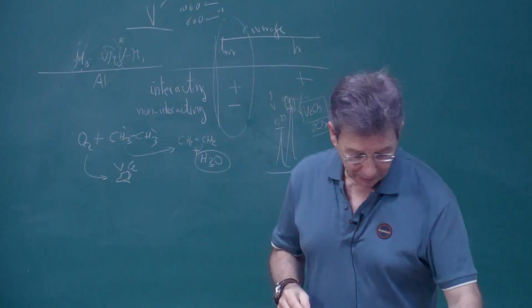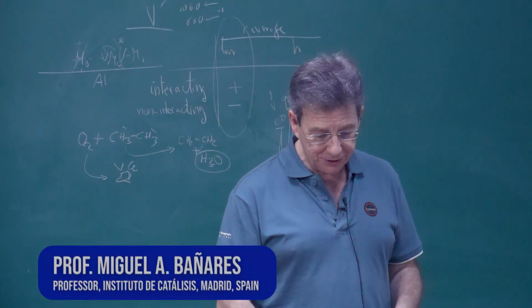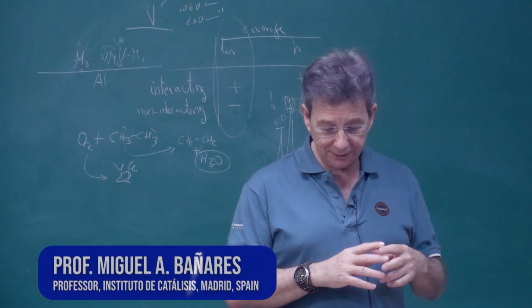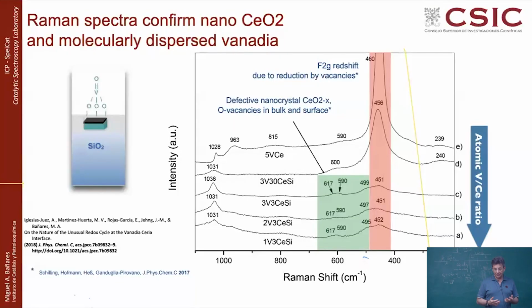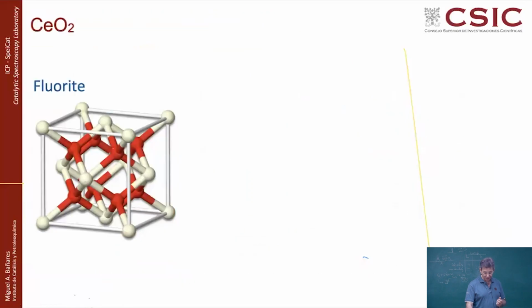That I missed, and I'm just showing it here, which is when we are using the nanoscale ceria on silica, you can see that you get nanoscale ceria particles mainly because they didn't show up in X-ray diffraction, but also when you were looking at the catalyst using Raman spectroscopy, in addition to the Raman bands of the bulk ceria, you could get a few additional Raman bands, very weak, which are associated with defects that are produced at the surface of nanoscale ceria particles. So Raman can also report on the presence of this. And actually you can see how the strong Raman band of ceria is almost missing and essentially replaced by bands associated with the highly defective ceria. So this is confirming this kind of a state.